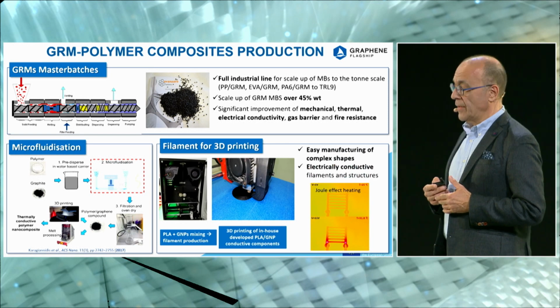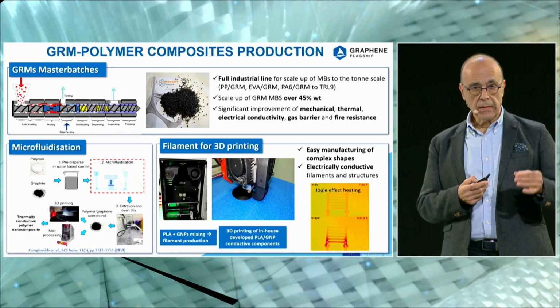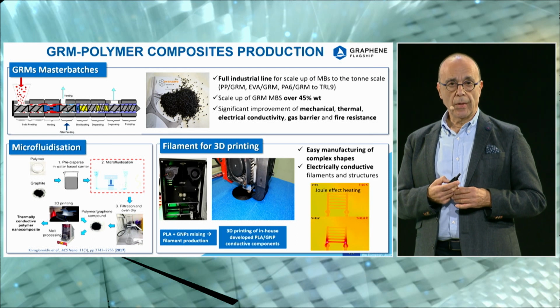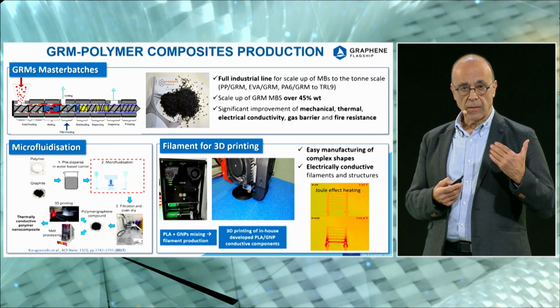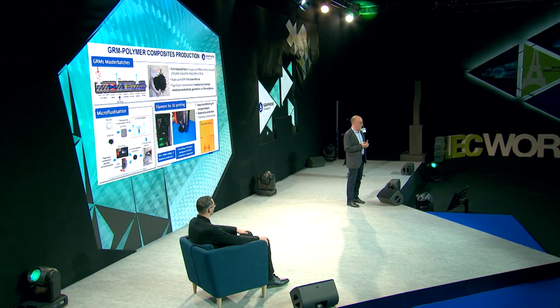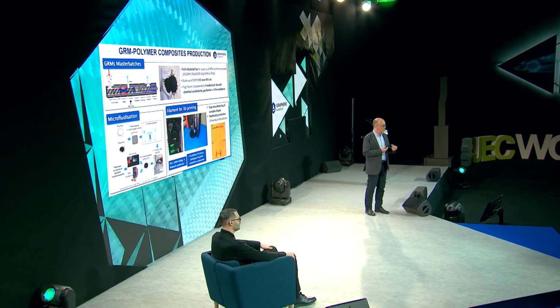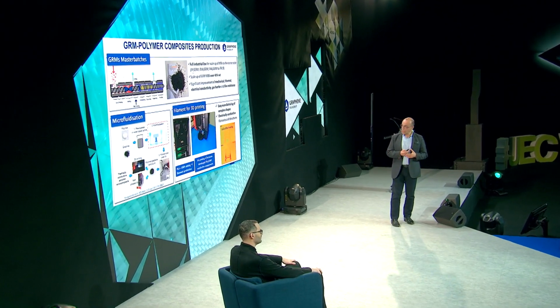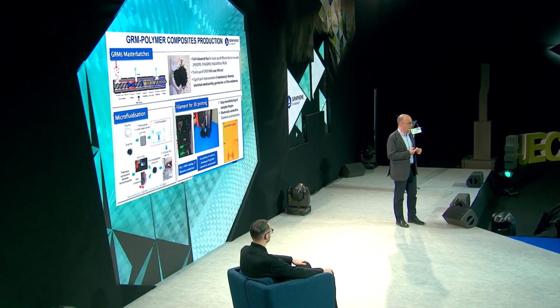Filament 3D printing, you can actually add graphene into a polymer. This is what we're doing in Greece, at the University of Patras and FORTH in Patras, where I come from. And you can build all kinds of heating devices using the 3D printed fibers, because the graphene being there is bestowing thermal properties and heat to the material.